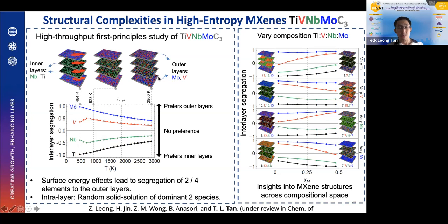So from this machine learned surrogate model, we can learn how these elements have a certain preference for inner layers and outer layers, and within each of the layers itself, the two elements, for example moly and vanadium, are more or less randomly mixed. So the short story here is that for high entropy alloys, there will be some separation, but within each of the layers itself, the 2 or 4 elements will be randomly mixed.